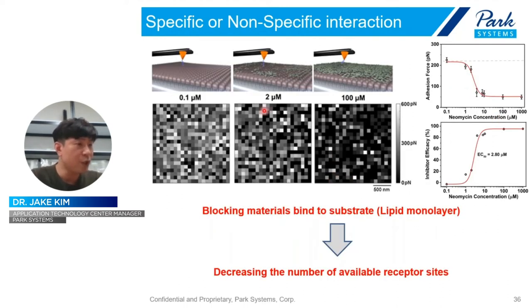And to prove this concept, we treat this blocking material on the substrate. Depending on the concentration of blocking material, the adhesion value decreases. And this dark area means a low adhesion value. It also means a decreasing number of available receptor sites, because this blocking material already interacts with this lipid monolayer, and there's no chance for interaction between the peptide and monolayer. This is just one application, but a quite famous and interesting application of FD curve and AFM tip functionalization.